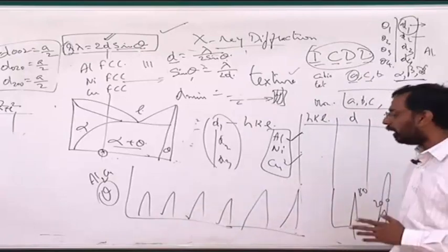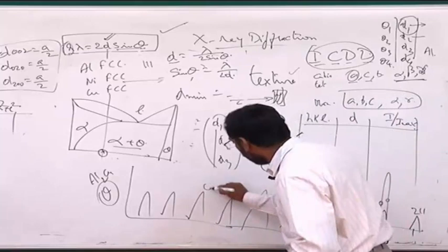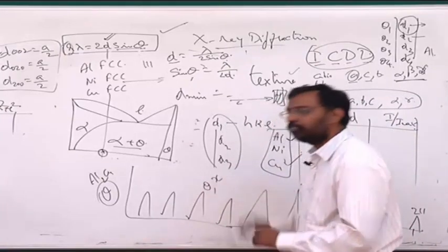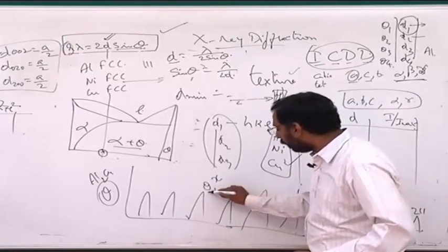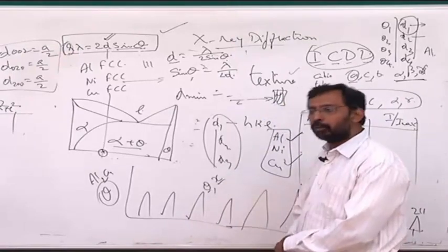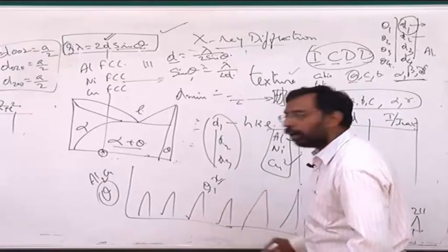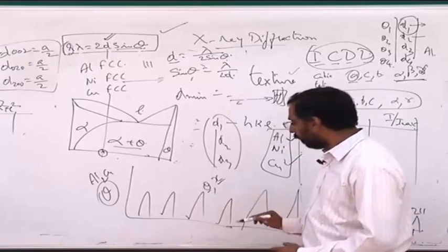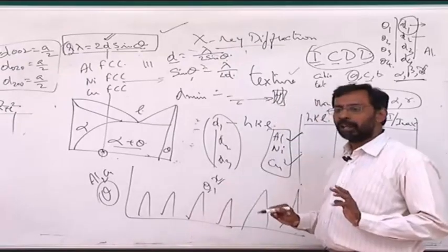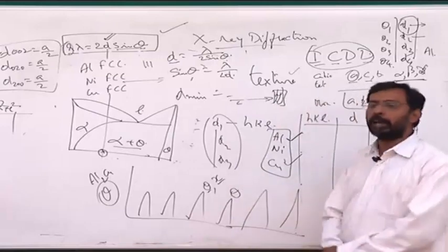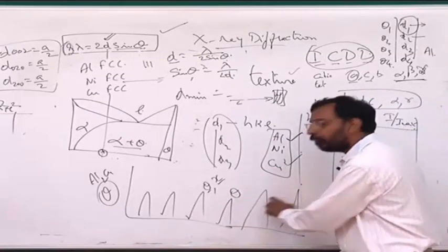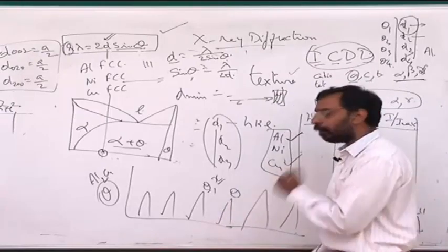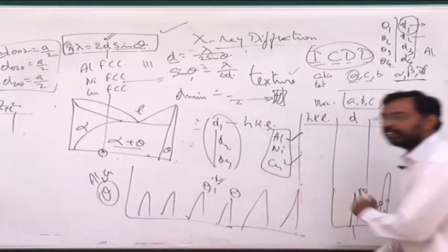The reason is, it is possible that this peak may correspond to theta, but may also correspond to some other X phase. How do I know that this is theta and not X? To know that, if it is matching with some other X, I should start searching for some peak where it is not matching with anything, and it should be exclusively a theta peak. And such a peak, if it exists, and I can find a peak at that particular position of the theta, then only I can say theta is existing.